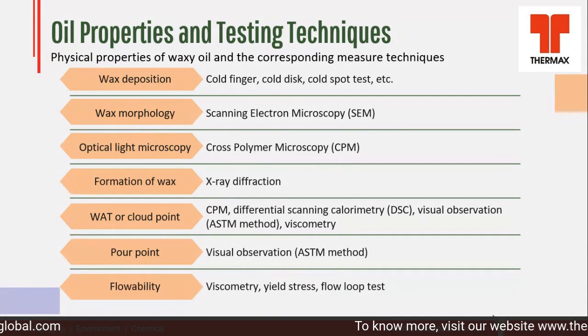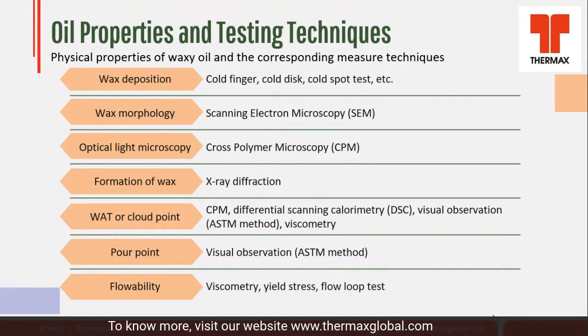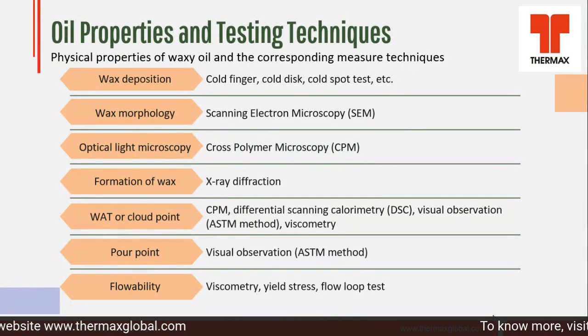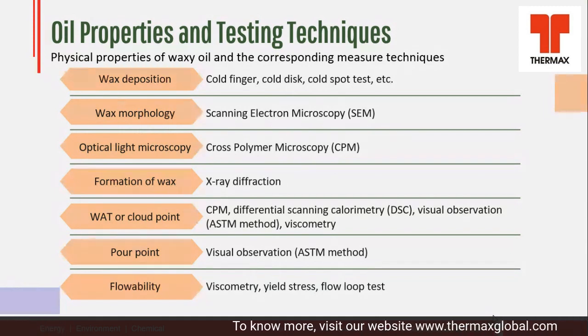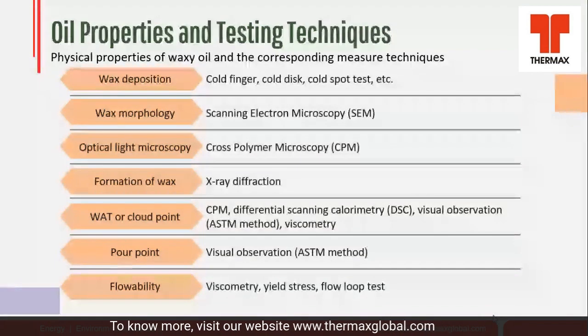Then pour point is tested with the ASTM D97 test method. And flowability can be checked with different viscometers or rheometers. And we can measure parameters like yield stress or plastic viscosity.